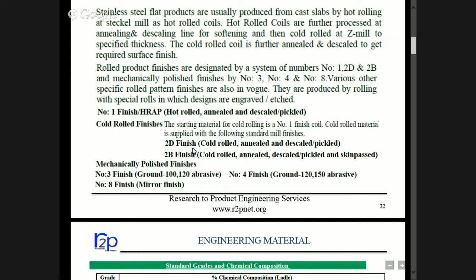As I was explaining, 2D finish is cold rolled, annealed, and descaled, pickled, and 2B finish is cold rolled, annealed, descaled, pickled, and then skin passed. Again, you can say cold rolling process done for finishing and sizing. And for mechanically polished, number 3 finish, it is ground with 100 to 120 grit size abrasive. Similar other finishes are there.